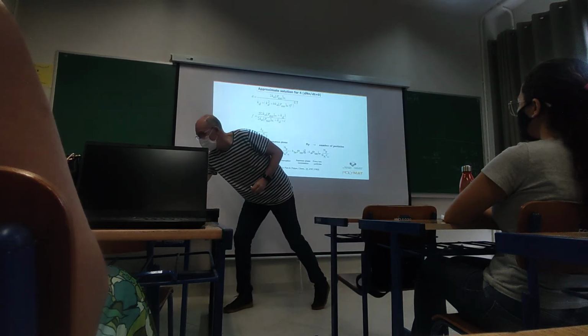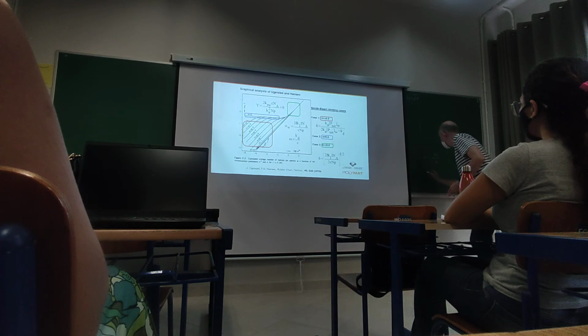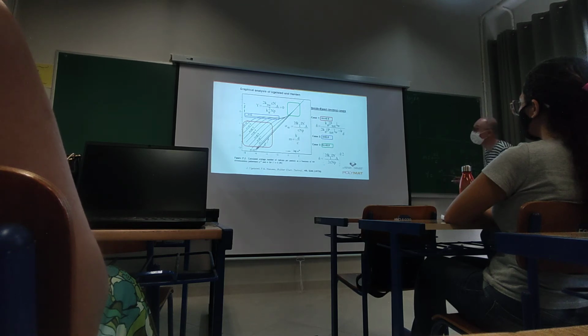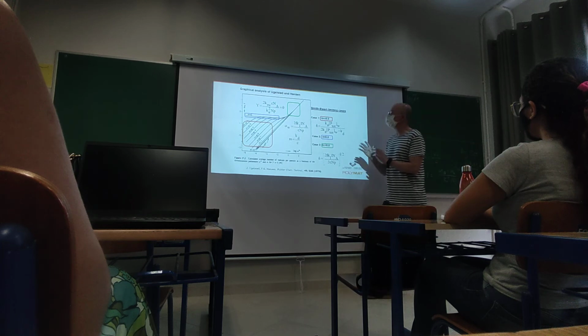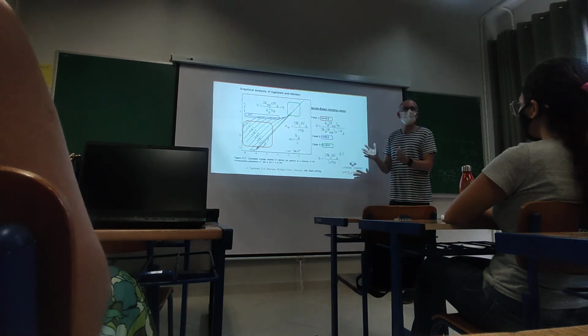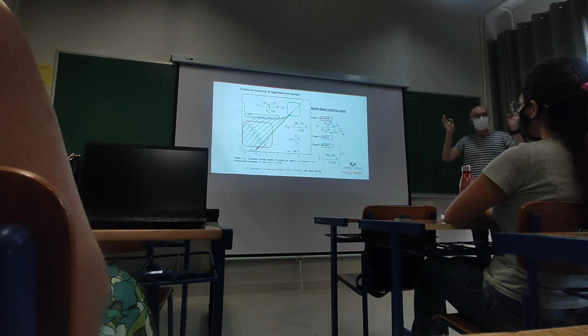And this is this Y, which is KT in the aqueous phase, C and A divided by K squared P, okay? This takes into account the probability of the radicals to terminate in the aqueous phase. How important is the termination of the radicals in the aqueous phase, okay? So these are the three parameters that basically control the average number of radicals in this equation.